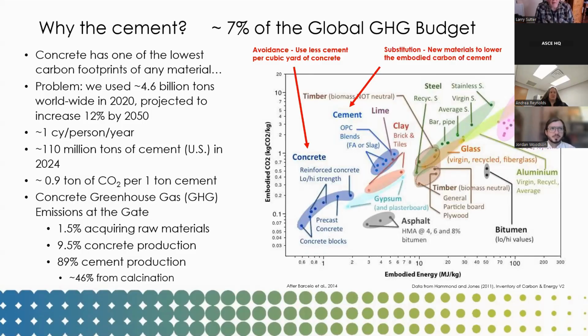And cement does result in significant carbon production. You get approximately a ton of CO2 per ton of cement produced. So we have to acknowledge that that's a fact. And the bottom line is that the majority of this carbon comes from the production of cement, 89% from production of cement. So affecting the cement is where we're going to make changes.